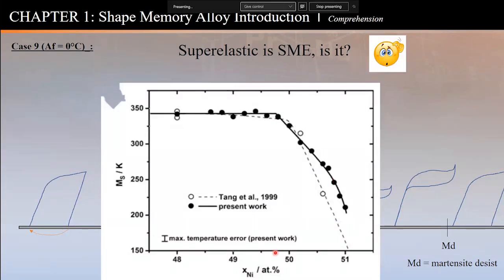So what I mean is, if I need an actuator that needs to do some function in the cold place of the moon crater somewhere, that is -50 or -40 degrees C, my actuator can be designed with this amount of nickel. If I'm going to be somewhere like in the hood of a car where it gets a little bit hot, it's not going to be cold, it's going to be hot, so I can design my alloy with 49% nickel or what have you, and create an alloy that transforms at higher temperature. So this is the game that we play in alloy development, and this is the simplest of them, nickel and titanium. Typically, we add a third element, a fourth element to tune this transformation temperature to a desired application. So if your application requires an activation at 200 degrees C, we can put some element here to move this line up and provide an alloy that can activate at those temperatures. That is the reason for having both elements.